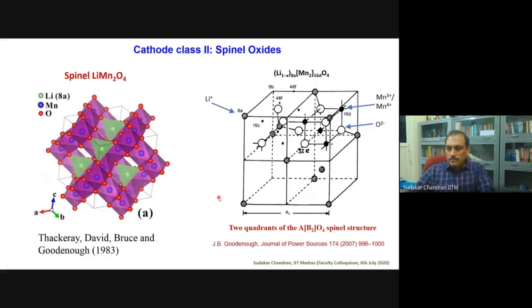So with that, let me move on to the second class of oxide materials, which came up from Professor Goodenough's group. Mike Thackeray, he was a researcher from South Africa. He showed that lithium can be inserted reversibly in Fe3O4 structure. It's basically the magnetic material, you all know it's lodestone. And till then, it was realized that you need to have a layered structure in order to insert the lithium very smoothly in between the layers. But then he showed that Fe3O4, which has a spinel structure, where the octahedra are connected in all directions, it is possible to reversibly intercalate the lithium.